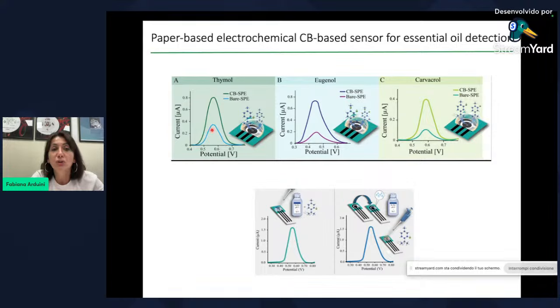In addition, also in this case, we demonstrated the advantage of using a paper-based carbon black modified electrode, because, for example, the blue line is the response in the case of the bare electrode, and the green line is the response in the case of the electrode modified with carbon black, in the case of thymol, and we obtained the same behavior in the case of eugenol and carvacrol, which are other essential oils.